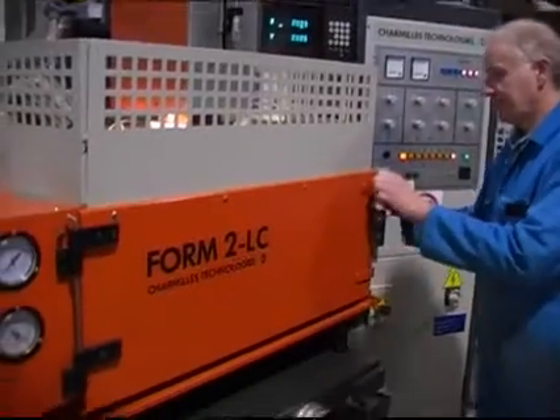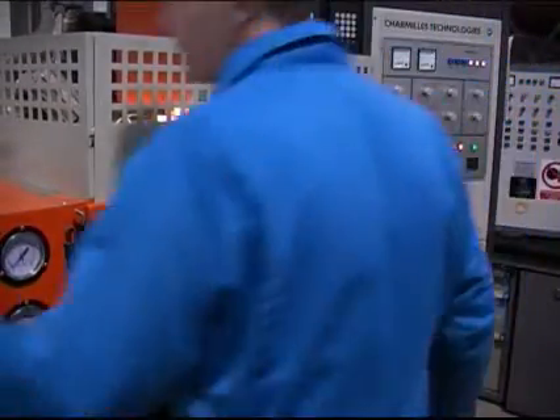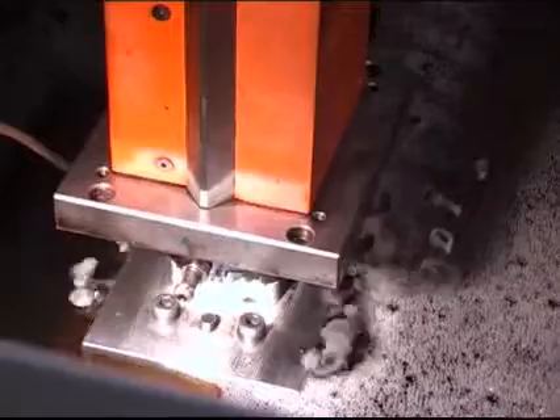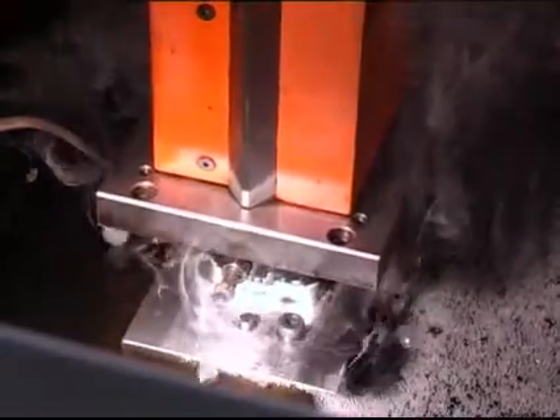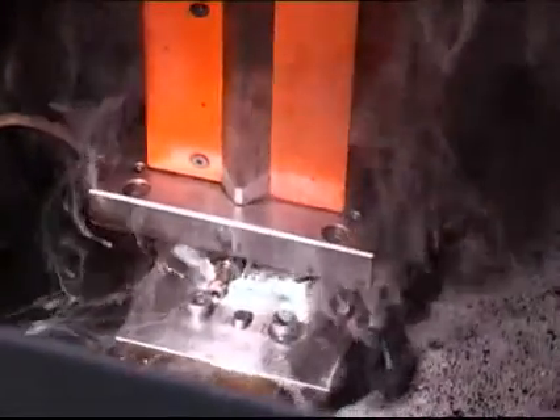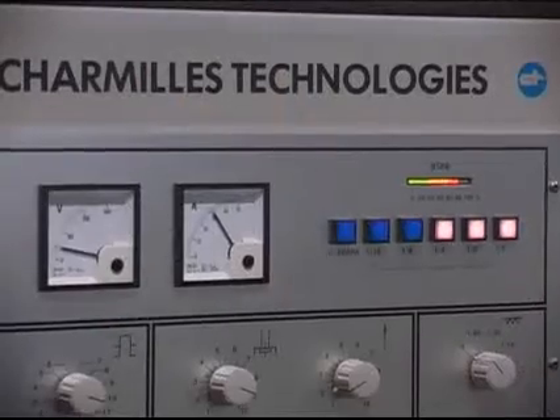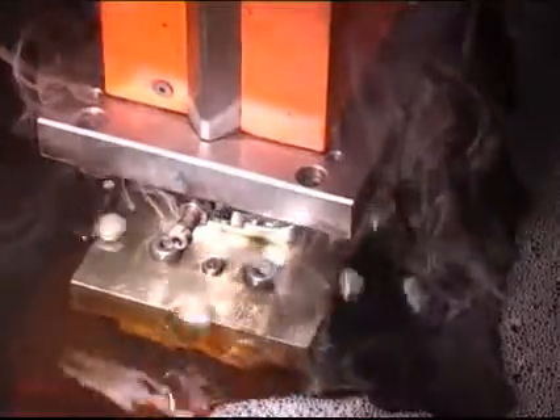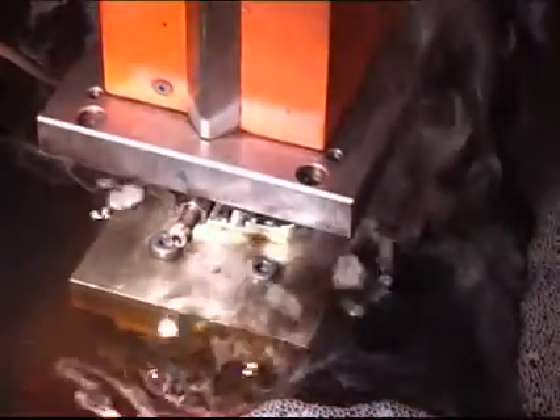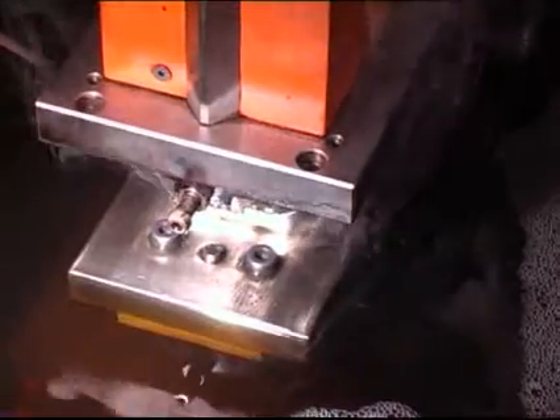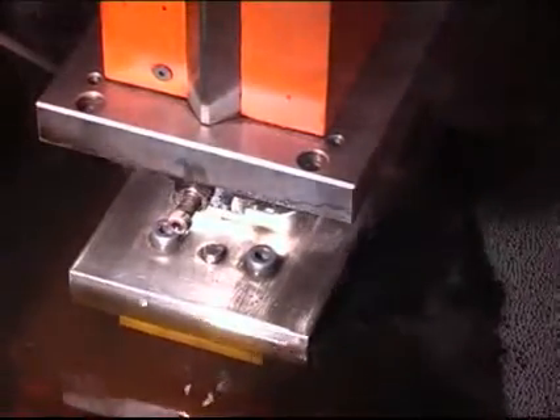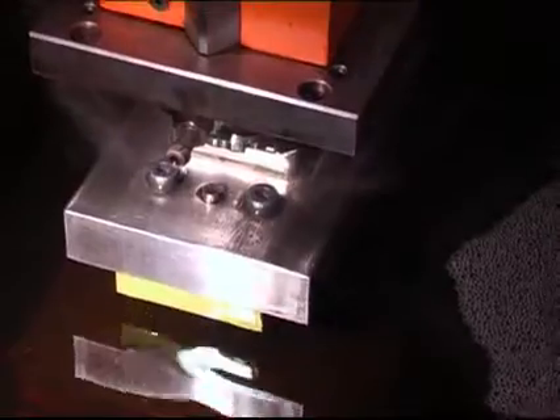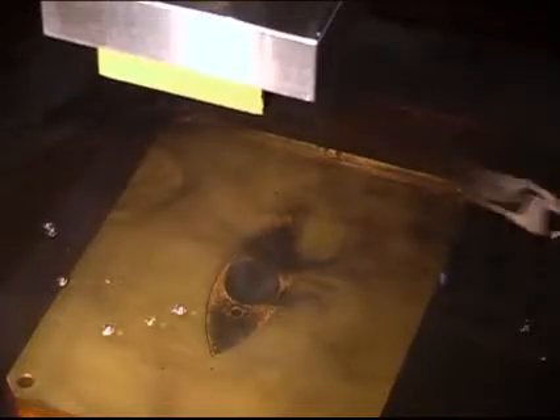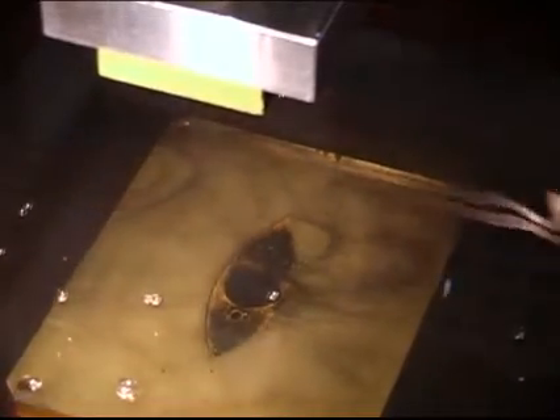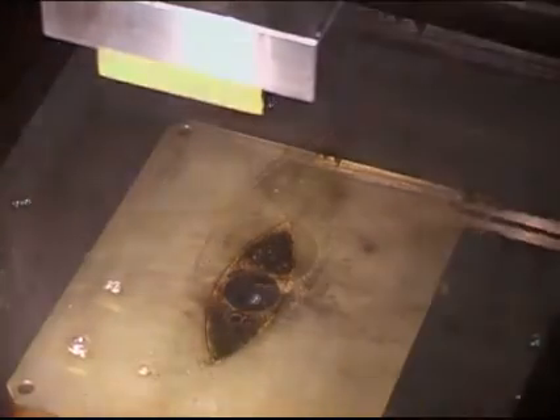The sealed door is then closed and the chamber filled with a water solution. The electrode is then brought down to the steel blank and a 30 amp 90 volt current eats away at the steel. When complete, the electrode is raised and the solution is drained. This process leaves the shape of the electrode eaten away into the steel blank.